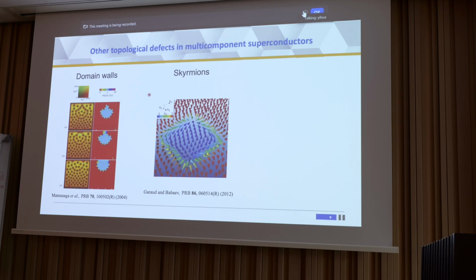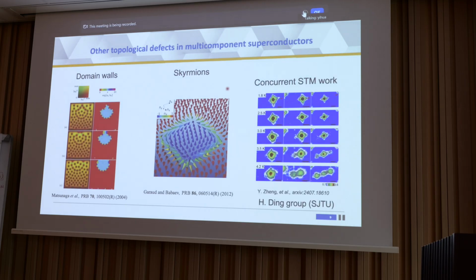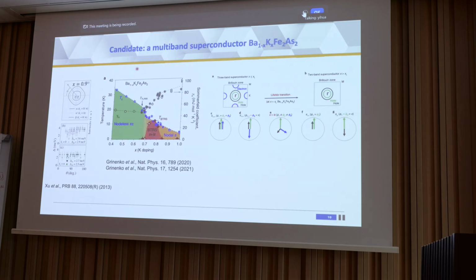There are many other consequences of having a multi-component order parameter, such as having domain walls in the order parameter or forming more exotic topological excitations, which are called skyrmions in a superconductor. And recently there is STM work, which you might hear soon, about the fractionalization of forming domain walls in these multi-component superconductors. The material platform to realize a multi-component superconductor needs to have multiple bands crossing the Fermi level. And the iron-based superconductor, barium potassium iron arsenide, is such an ideal material platform.